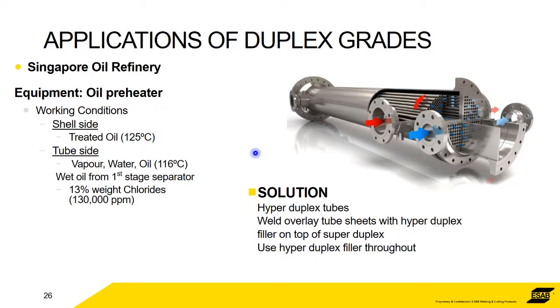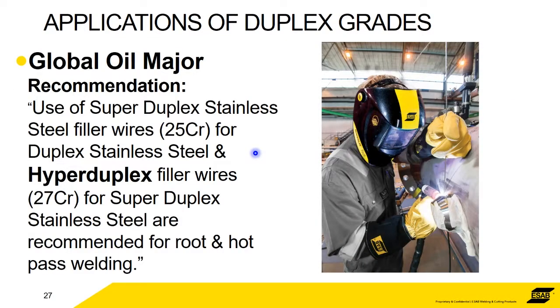The result was that rather than buying all that nickel, they bought basically stainless steels. They saved over $8 million. So it's an excellent application that we've got. We do have a global oil major that's written a report specifically about welding, and they absolutely recommend overalloying. If they're welding duplex pipes, then they recommend welding with super duplex. So it's an overalloy. You're welding a 22 chrome with a 25 chrome overalloy. However, the interesting part was that for any super duplex welding that they have, they recommend using hyperduplex filler wires. So that's really good for us because hyperduplex is only available from ESAB.